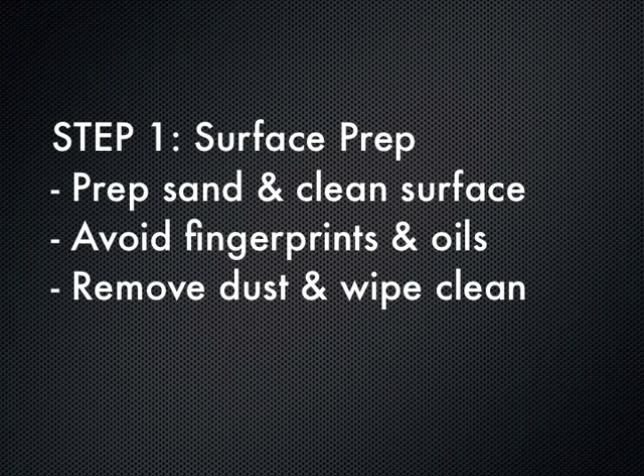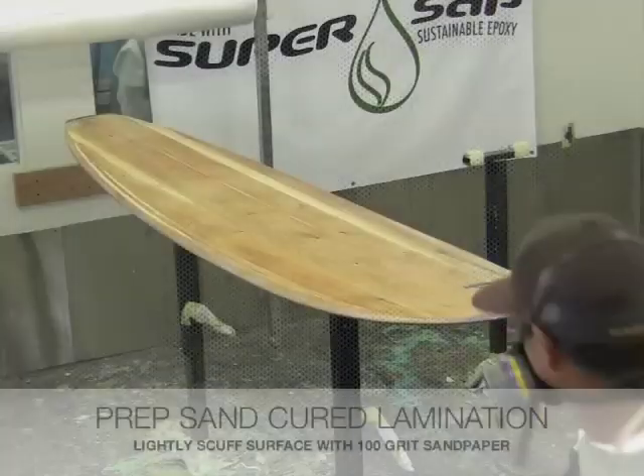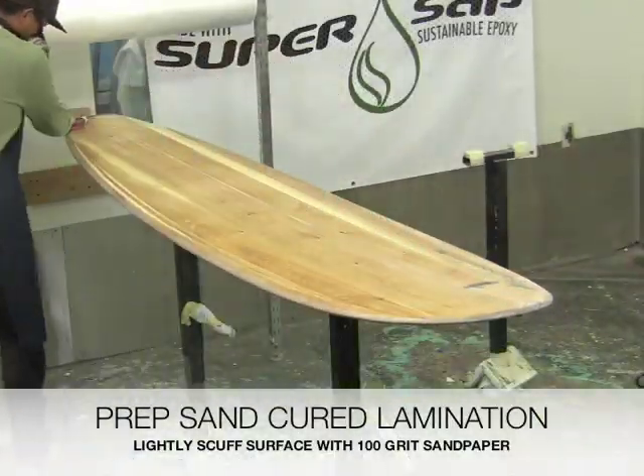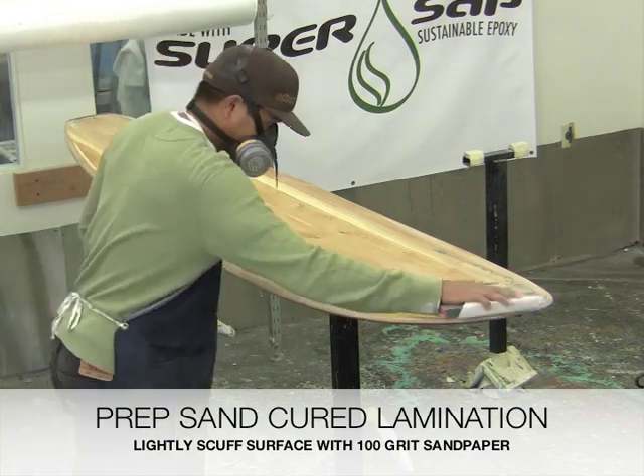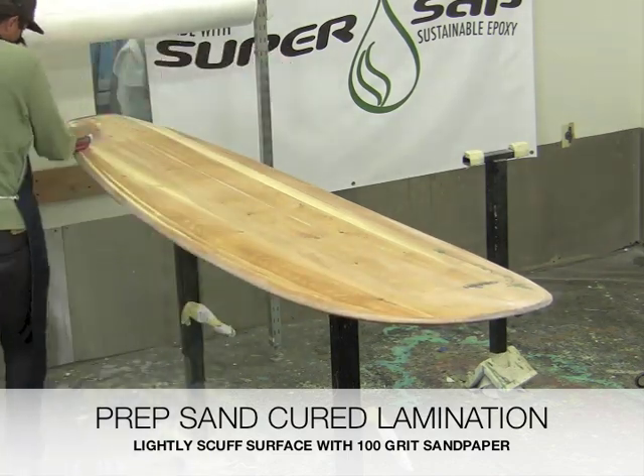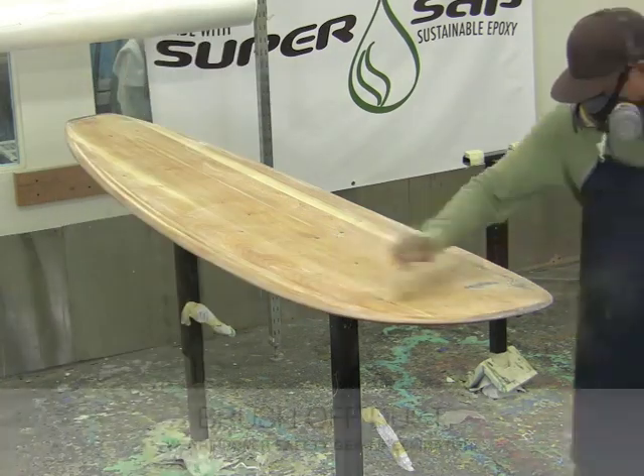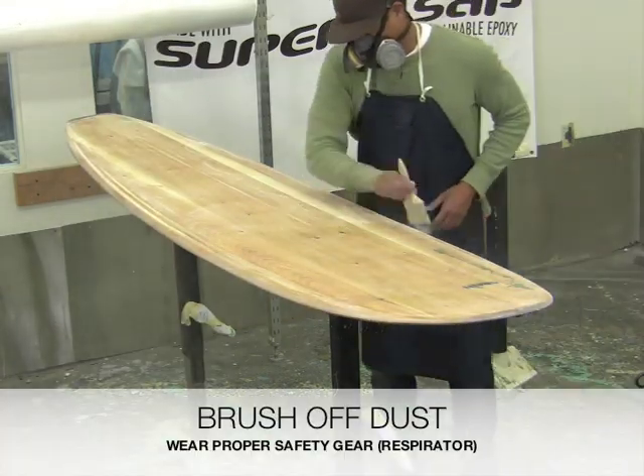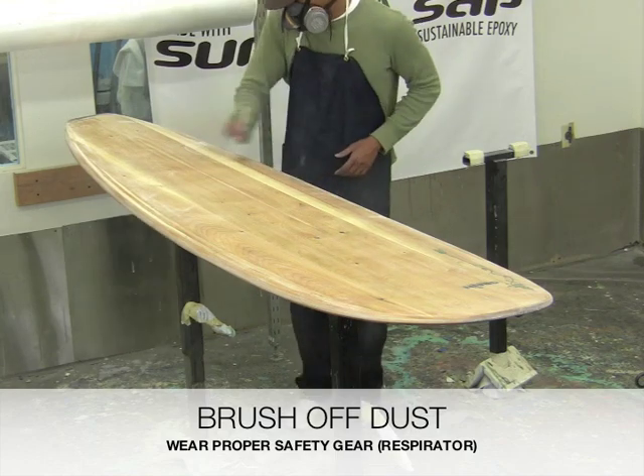We'll begin by prepping the surface of our cured lamination and keeping it free from oily fingerprints that could create surface blemishes in the hot coat. Create a mechanical bonding surface for the hot coat by lightly scuffing the cured lamination with sandpaper. Then remove the sanding dust with a clean, dry brush.